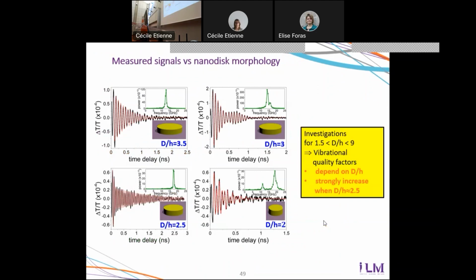So here each signal corresponds to a measurement on an individual nanodisc with, however, different diameter over thickness ratios. Here, 3.5, one vibrational mode detected. 3, beating pattern due to the fact that we have two close vibrational modes which are detected. 2, which corresponds to two vibrational modes which are quite far in frequency. And the most interesting situation is here. You can see we detect one vibrational mode, but we see much more oscillations than in other cases before damping is complete.